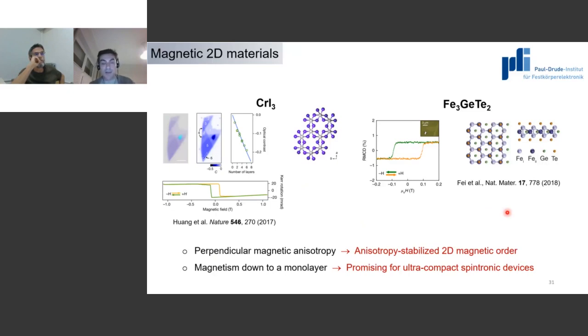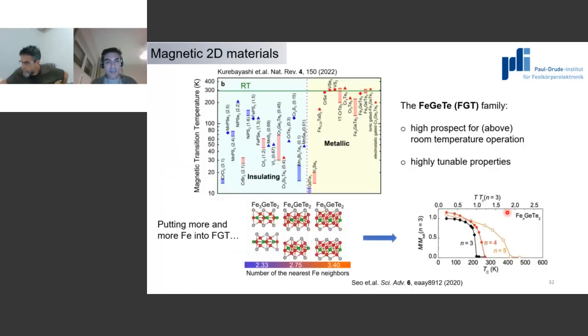and this probably is what allows for the stabilization of this two-dimensional magnetic order. And of course, as always in these atomically thin materials, if you have a magnetism that survives down to a monolayer, that is immediately something very interesting for the design of a new generation of spintronic devices that are atomically thin and so on. So a lot of interest emerged in this new type of 2D ferromagnetic materials.